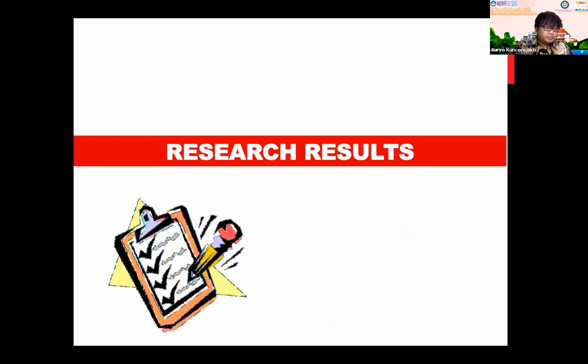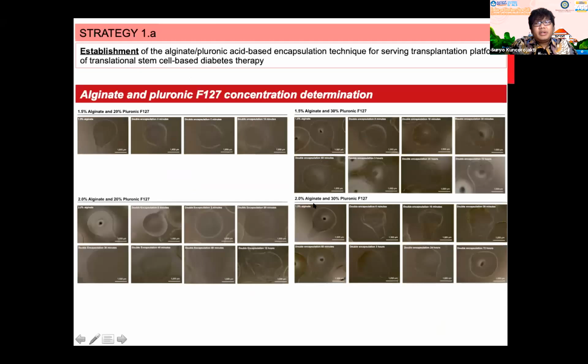Then how about the result? So the first strategy is the development of the encapsulation platform. In this study, the alginate and pluronic concentrations were determined. At that time, we used 4 different platforms. The first platform is 1.5% alginate and 20% pluronic. The second platform is 2% alginate and also 20% pluronic. Another platform, 1.5% with 30% pluronic. And the last platform is 2% alginate and 30% pluronic. Let me show the result.